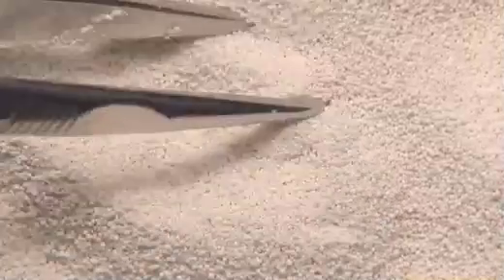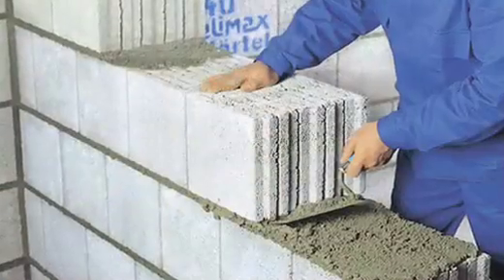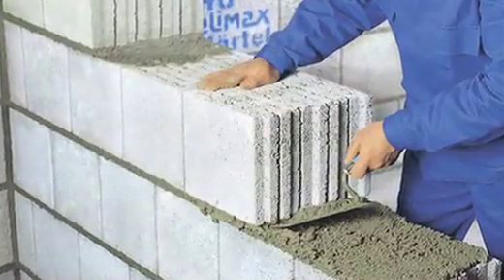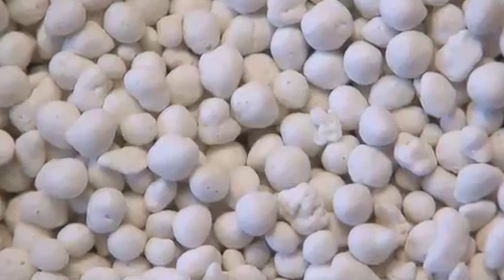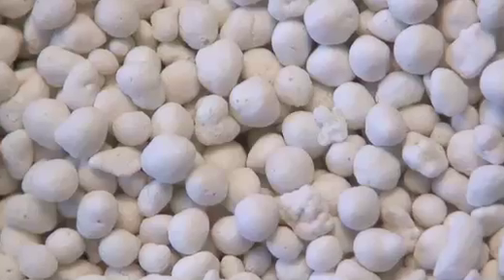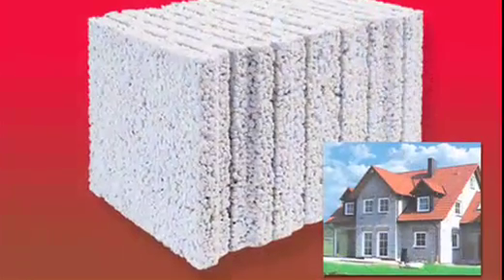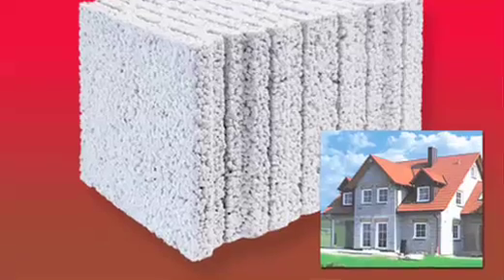The other great attribute of this product is there's very little water absorption. So if you're making a wet mix, a wet slurry, and you're trying to produce poured cement, poured gypsum, block, there will be no issues with increased viscosity in your mix. The only way you could increase viscosity is if you leave the product in water, let's say over 48 hours, and you may get some capillary action occurring, and that's when you will see increased water absorption. But for actual mechanical mixing in a slurry, you have absolutely no issues, and you will not be required to add more water, so you can actually get down to the lowest possible water content for proper hydration of cement, let's say at 28%.